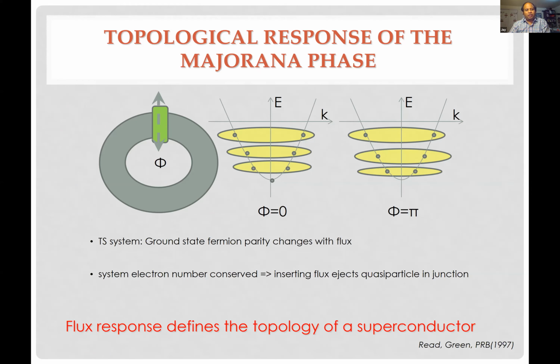Another very fascinating property, actually a defining property, of the topological Majorana phase is the so-called flux response. So I told you that an example of a Majorana topological superconductor would just be a spin polarized superconductor. If I could pair them up into Cooper pairs in momentum space, this is what I would get. The interesting feature is that that state would have one electron that is unpaired at zero momentum. If I introduce a pi flux for electrons, that phase shift would remove the electron at k equals 0, and I would now have an even number of electrons.